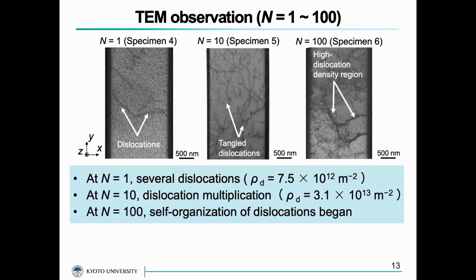After the first cycle, several dislocations were observed in the specimen. However, the dislocation density was not apart from that of annealed metals. But after 10 cycles, the number of dislocations increased in the wall region of the specimen. Some dislocations tangled or intersected each other. After hundreds of cycles, the number of dislocations still increased, and self-organization of dislocations began. Self-organization of dislocations produced this black high dislocation density region in some parts.